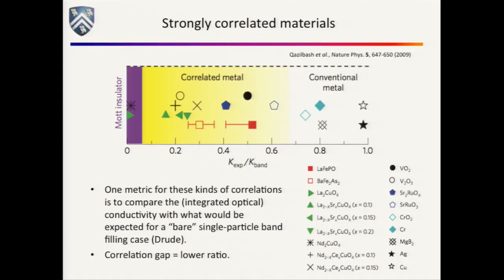At high temperatures, VO2 is a metal, but it's a metal that seems to violate the Ioffe-Regel criterion, so it's got a peculiarly high resistivity. And then you've got systems down here in the really more correlated limit that are things like these cuprates. Interestingly, the iron pnictides are somewhere kind of in the middle. So this is one way of quantifying how correlated these things are. The idea is that the spectral weight that would have been in the Drude peak is somehow transferred up to higher frequencies. You're sort of gapping things out at low energies.